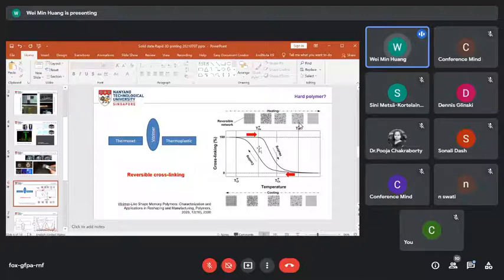Now let's take a look at the internal structure. This is an illustration of the reversible cross-link, and this is the percentage of cross-linking, and this is temperature. If we heat up to this temperature, which is well above its melting temperature, later I'm going to explain in an example what the melting temperature is, the temperature at which the material starts to melt, start to flow. So if you heat up, cross-links start to gradually disappear until upon heating to over here, there isn't any cross-linking anymore.